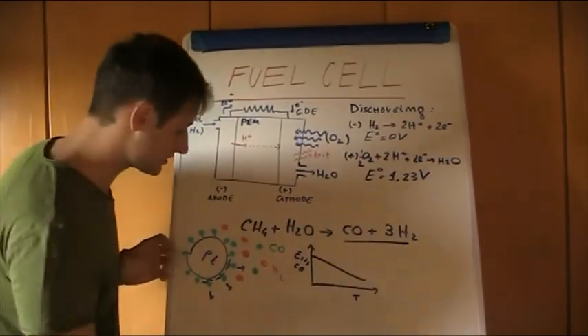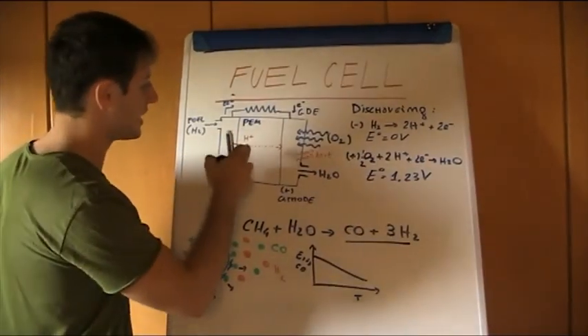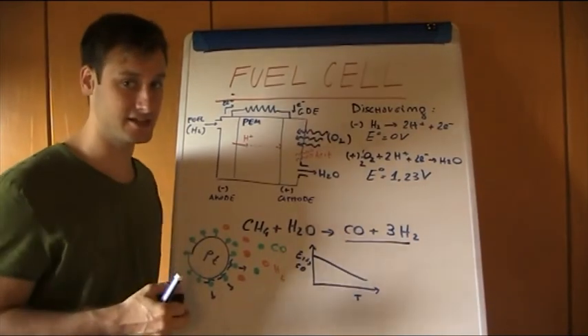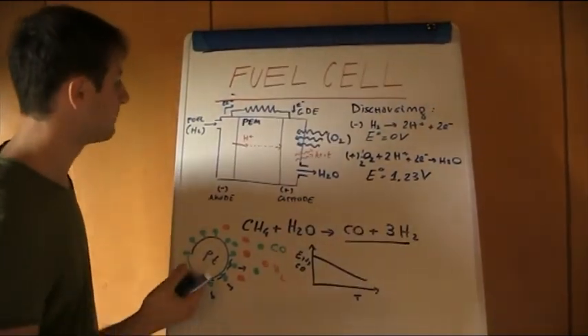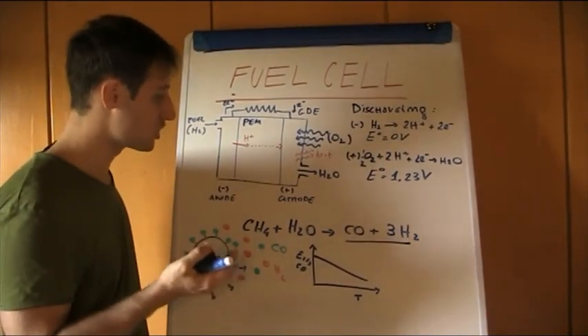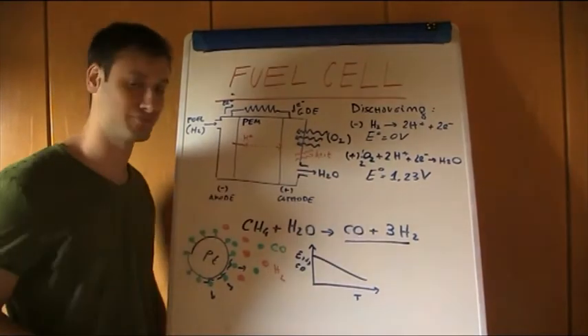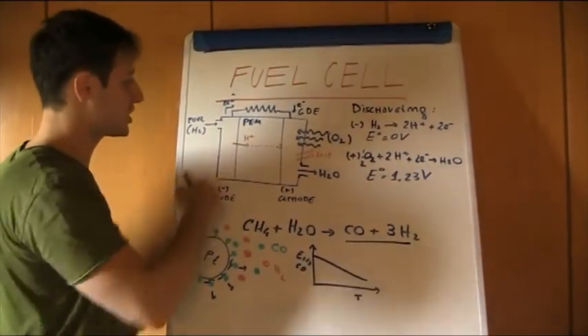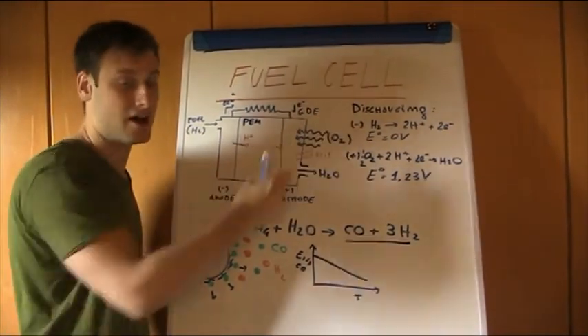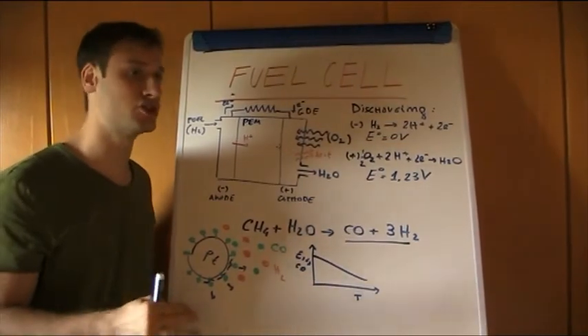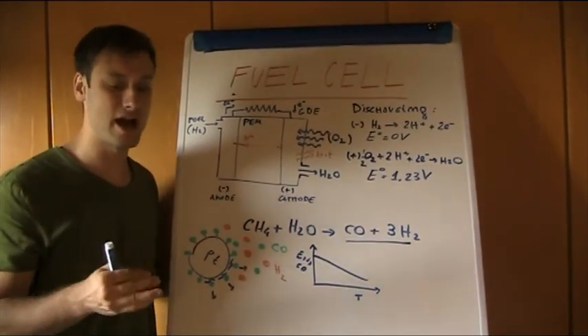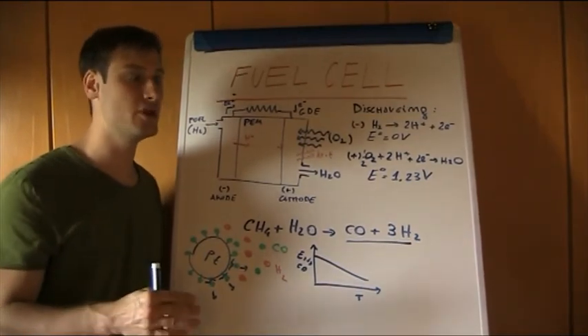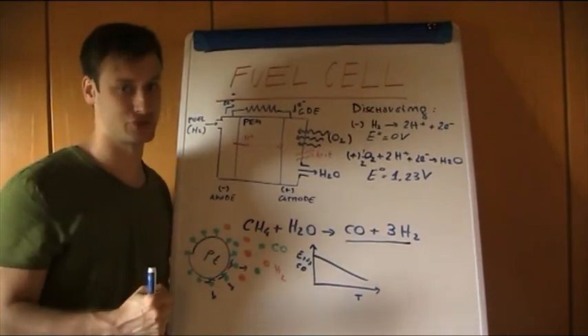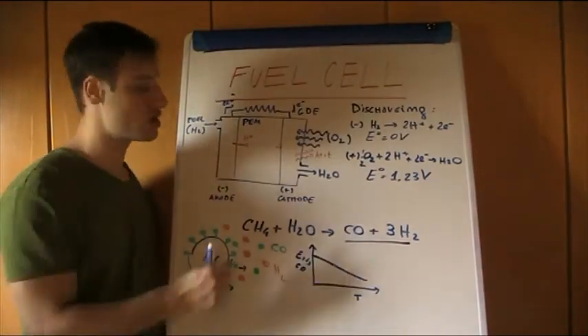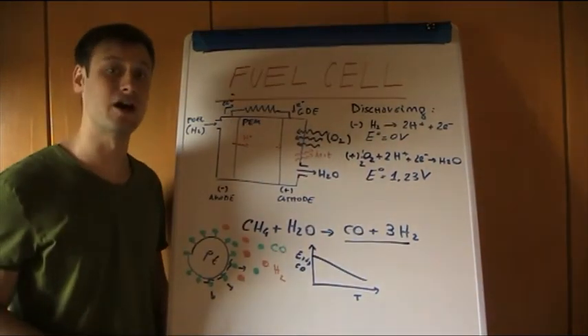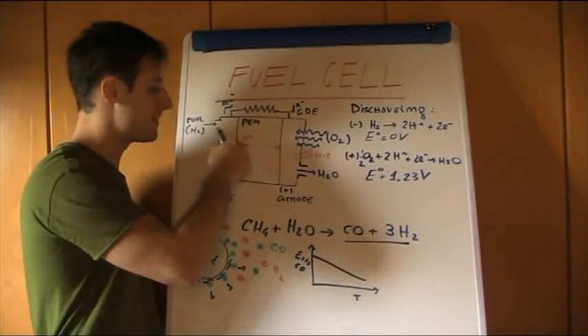So basically, another extremely important thing to say is that this ionic membrane is working in a wet state. It should not be dried in order to ensure the passage of H+. For this reason, proton exchange membrane fuel cells are basically working in a range of temperature that should not be higher than between 50 and 100 Celsius degrees. In general, we need to be lower, often 80 Celsius degrees. Why? Because if you increase the temperature too much, we are promoting the drying of this type of membrane, and we are not able to promote anymore the passage of H+.